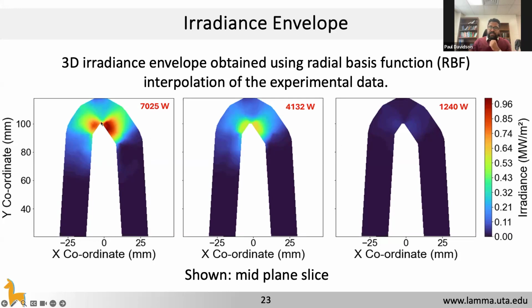As you can see, the profile itself is similar as you change the wattage. But within one wattage, it is extremely nonlinear. And a tape, or material point, is essentially passing through this nonlinear flux profile. So it is not the same incident radiation; the radiation changes as the tape moves through this flux profile, right? So that becomes a very complicated problem, because now the material does not see the same flux, and the time history of the flux now matters, right?